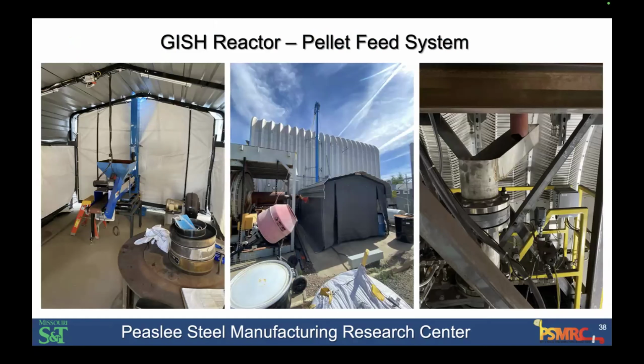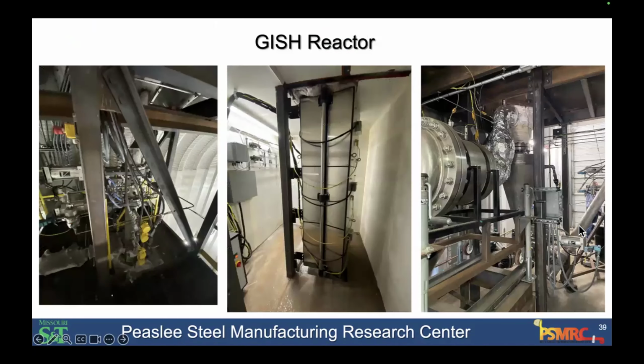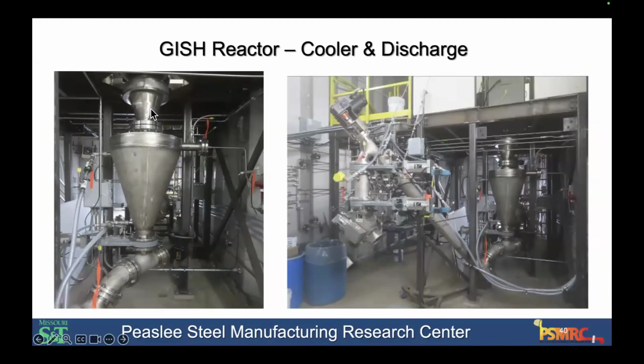This is just a step through the reactor system. The lower left is the ore pellet feed system. We have a conveyor system that takes it up to the top of the reactor, feeds it in the top, and feeds it into the shaft. That shaft then has an interlock to take it into the hydrogen environment safely, and then passes down 1 story through a heated zone in the reactor, and then through to the bottom where we have a discharge system and the gas injection component of the system, where we have the gas preheater injecting the hot gas that can be hydrogen, natural gas, or a mixture of the two. And then at the exit system, we have a cooling system that allows the DRI pellets to be cooled and extracted and then packaged in drums.